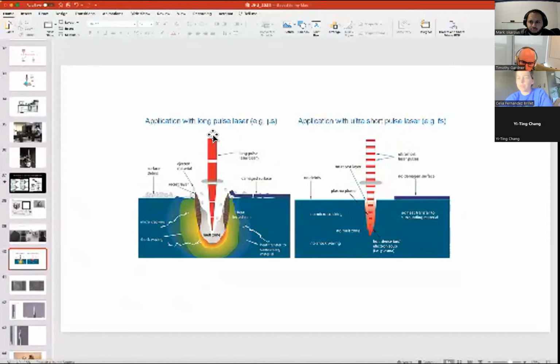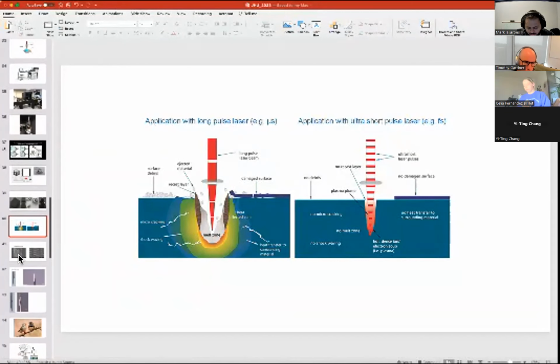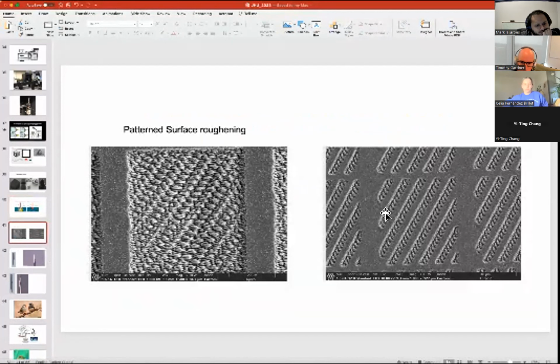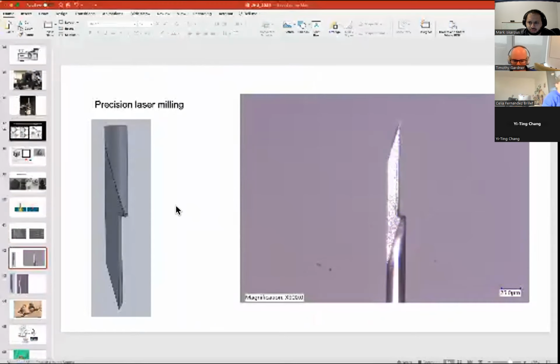So if you think about laser cutting, typically it's a really complex process. You're generating a lot of heat. But if you go in with femtosecond pulses, particularly high amplified high energy pulses, you can just tear apart the atoms in a way that leaves no heat affected zone. So it just vaporizes the material, and you can get really, really smooth laser milled surfaces. And this is just an example of some very precise pits that we cut on silicon wafers using a Monaco laser. This is an amplified ultrafast laser, and it's the way that I built the needles for Neuralink, where we use a raster scanned laser mill that allows us to achieve extremely high resolution in the needle shape as shown here.